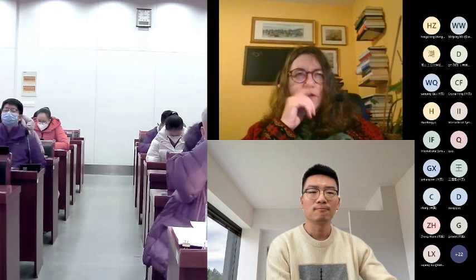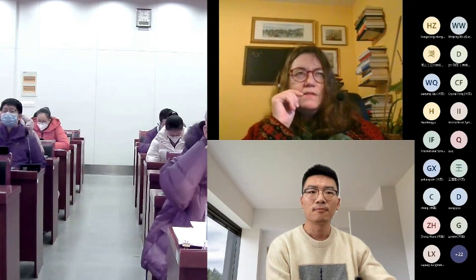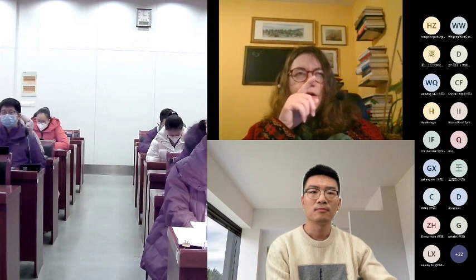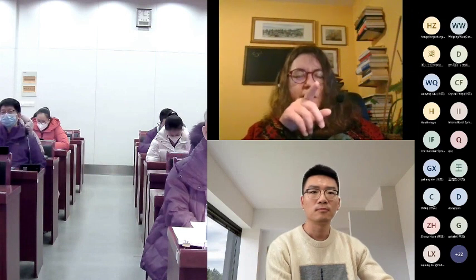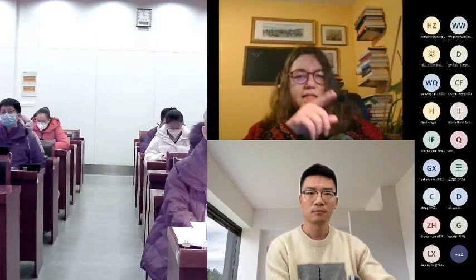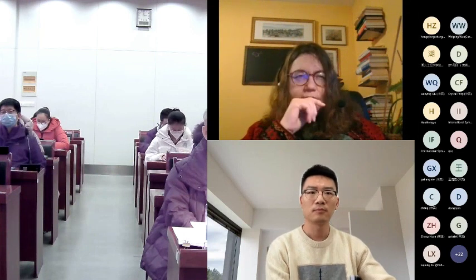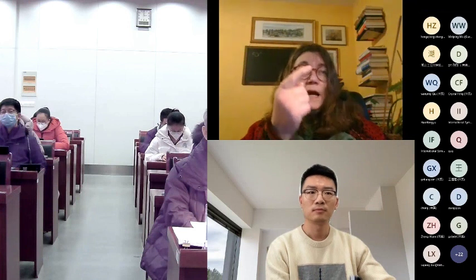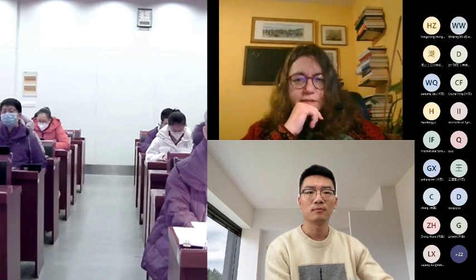Let's think. Important is that we don't get the phosphate by absorption first. So during hydrothermal carbonization we convert everything to acid soluble phosphate. This is magnesium calcium phosphate, and then we precipitate this as struvite, and we get 80% of the struvite. In the end, only a few percent of the material is phosphate. The content is relatively low.